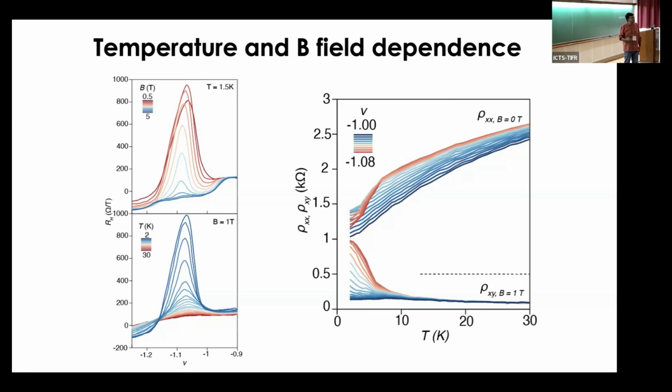And so our evidence that this is a real phase is from this sort of behavior. If you go to high enough temperature, all of this behavior disappears, and it more or less matches the non-interacting expectation. And if you apply a magnetic field, then with a reasonable magnetic field, again, you can quench this behavior, which is our evidence that this is somehow a magnetic phase. Okay? And let me just tell you what we think this is.